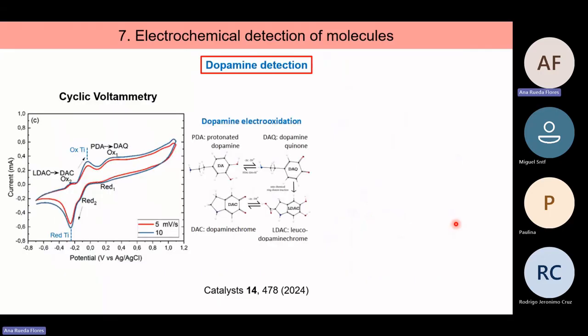So with cyclic voltammetry, this is what we got for two different scan velocities. In the oxidation branch we can see three peaks. One is the oxidation of the titanium nanocolumns, but the other two peaks correspond to transitions of the dopamine electrooxidation cycle. And in the reduction branch, of course, we have three peaks: two reductions of this cycle and the reduction of the nanocolumns.